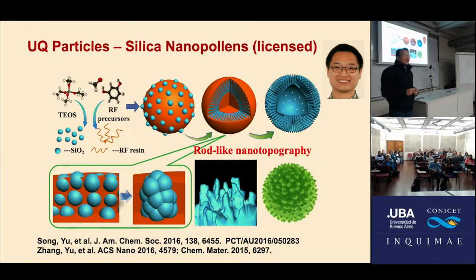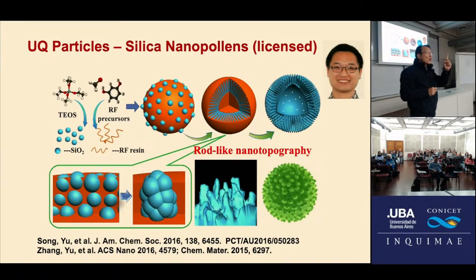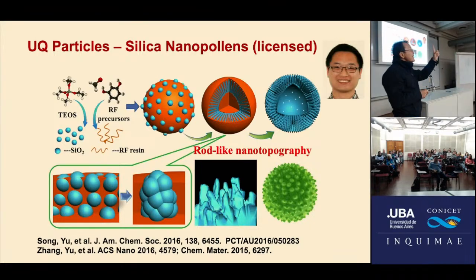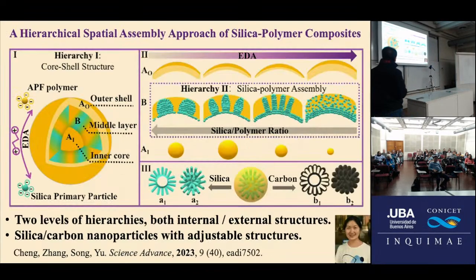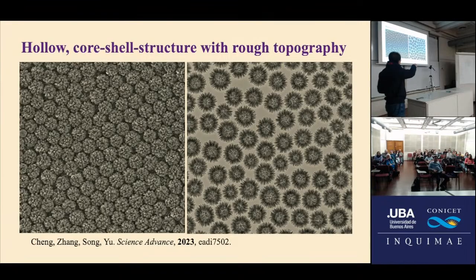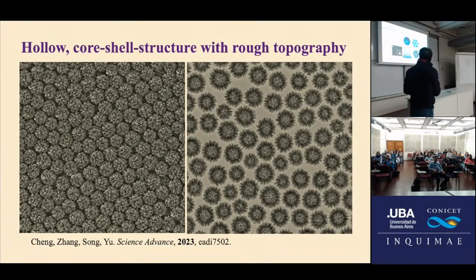In the previous one, we used particles with different sizes for the preparation. Afterwards, we developed a molecular assembly strategy. For example, we only use TEOS and some polymer precursors, using the TEOS and the polymer self-assembly to get these silica nanoparticles with rough morphology. I have to mention that right now the nanotopography is different. In this case, we have this finger-like nanotopography. Previously, we had a semi-spherical-like nanotopography. We have some work showing the nanotopography difference is also important in terms of their interaction with cells. We follow this track and use different polymers to assemble these particles, so we can prepare silica nanoparticles with rough surface with quite a uniform and controllable structure.